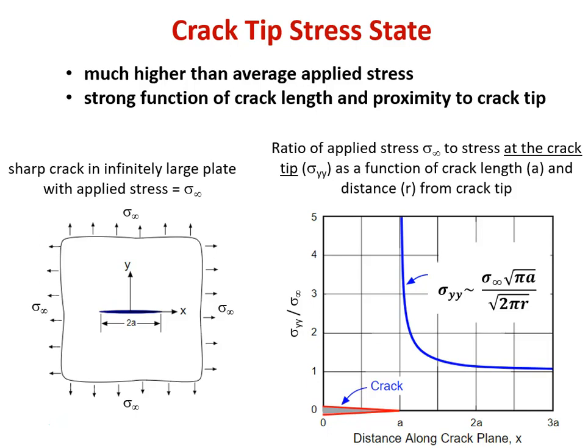Now remember, if you're designing a material, you can only control what's applied to the edge of that material, or macroscopic stress application. You can control sigma infinity, but what's going to propagate the crack is the sigma yy that you see on that right-hand diagram. We're talking about what's going to make a crack spontaneously propagate. It's the stress state right at that crack tip that matters. And that's why there's a whole discussion in this section and a whole field of fracture mechanics that tries to calculate that.